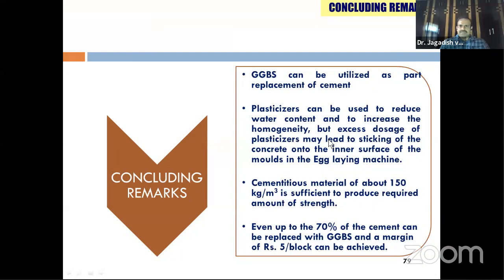and plasticizers can reduce water content, and it will increase the homogeneity. You can use them, but you should not use excess because it may stick to the egg laying machine sides. From the experiments we understood the cementitious material of about 150 kg is sufficient to produce the required strength. One need not go beyond 150. And up to 70% of cement can be replaced using GGBS.